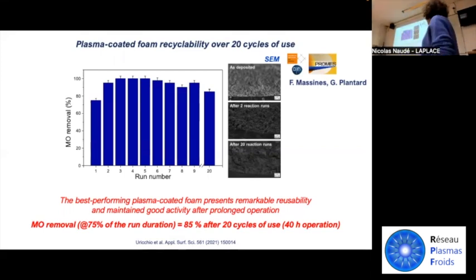That is, after 20 cycles of use and 40 hours of operation, you can appreciate after 20 reaction runs that the nanoparticles are still present. And the collaboration with PROMES really helped us to evaluate and characterize the material after 20 reaction runs.